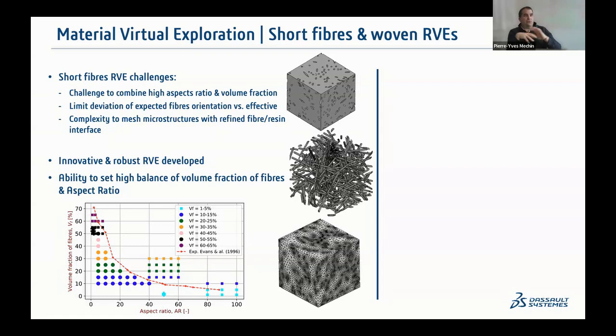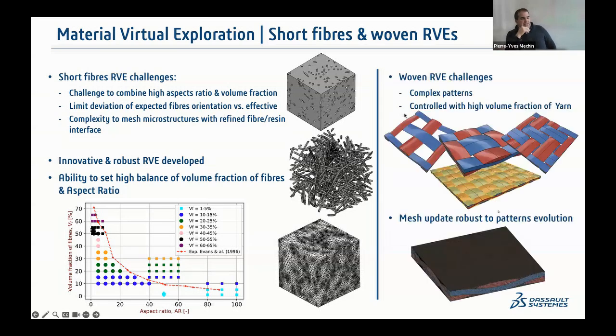Basically, this is a view of the fibers randomly arranged with a control of the orientation tensor for the fibers, and the resin system around, which is well controlled from the mesh point of view. So just to show that we have an accurate RVE, which is efficient compared to some solutions I've developed in the past. Also the same for woven.